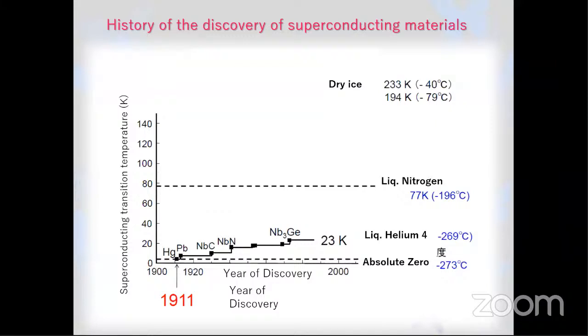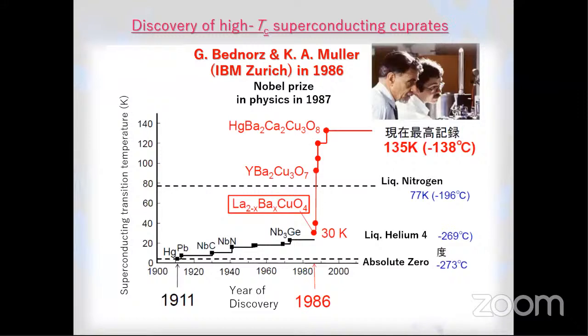In 1911, Kamerlingh Onnes found the superconducting state in mercury. After that, lead, niobium carbide, niobium nitride, niobium germanium, and the Tc became up to 23 Kelvin, but that is still only a little higher than the liquid helium temperature and below the liquid nitrogen temperature. Very recently, the transition temperature has become drastically higher than the liquid nitrogen temperature with high-Tc superconducting cuprates. Bednorz and Müller found the cuprate, lanthanum barium copper oxide, which is a ceramic. The record of the transition temperature is now 135 Kelvin in the world, higher than liquid nitrogen.